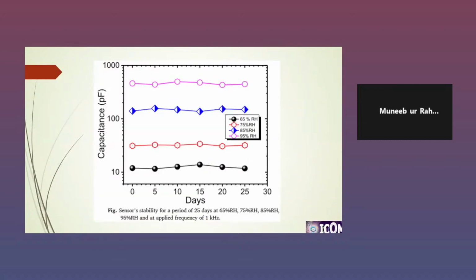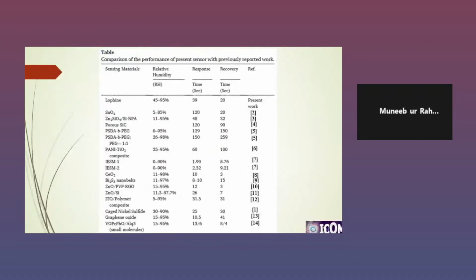This is the stability of our sensor, and we tested it at different humidity levels for different days, and we see that the stability of our sensor is quite good. This is the comparison of our result with other reported results available in the literature, and we see that this compound, having a response time of 39 seconds and recovery of 20 seconds, is quite good in comparison to the SnO2 material used for sensing, whose response time was 120 seconds and recovery time was almost comparable to our results. Similarly, there are some other materials which have better response and recovery time than our case.